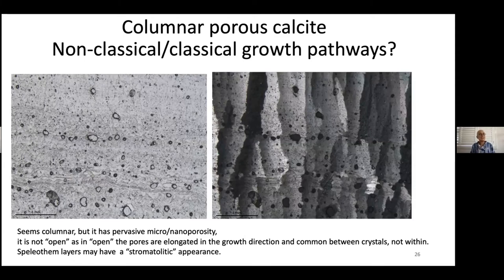Well, first of all, you see a fabric with pervasive porosity. Then what you see is that sometimes it even has some stromatolitic-looking features. So you might think that there are organic compounds, and there could even be bacteria around. But the most important thing is to look at where the porosity is.